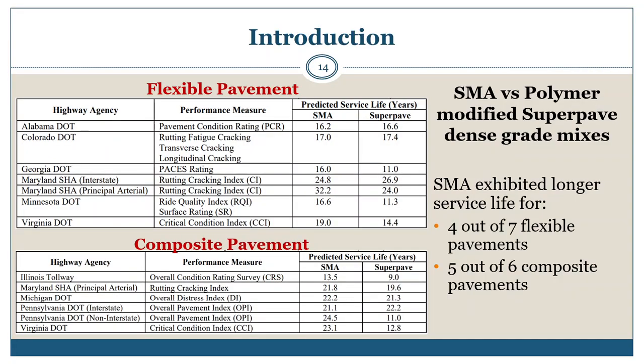This slide is simply a summary of the previous 2 slides as illustrated. SMA mixtures have lasted longer in comparison to dense graded Superpave mixes. In general, 4 out of 7 flexible pavements with SMA surfaces exhibited longer service lives, and those were significantly longer service lives. The 3 out of the 7 for the Superpave mixtures that had longer service lives were only slightly greater service lives. For the composite pavements, 5 of the 6 studies reported significant increases in service lives of the SMA mixtures as compared to the Superpave dense graded mixes.